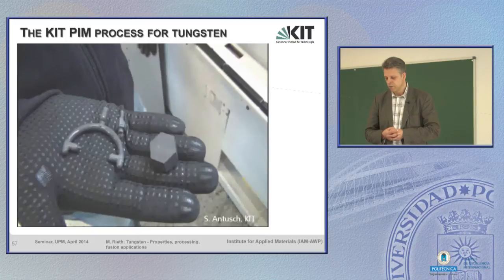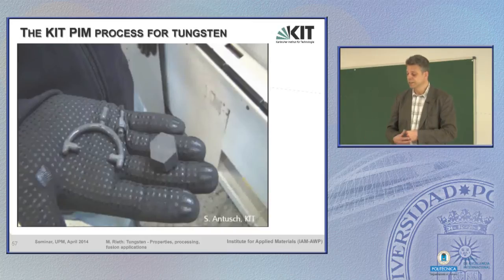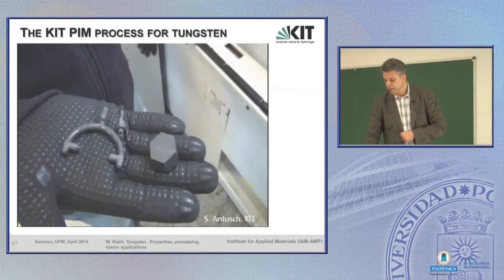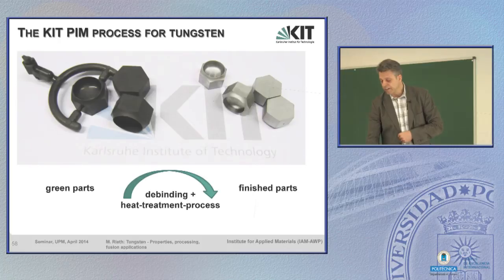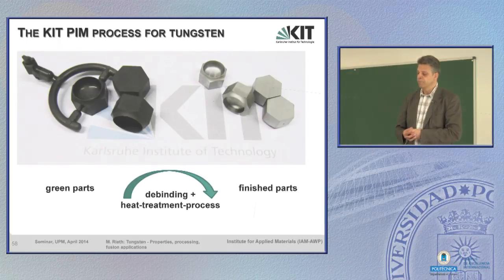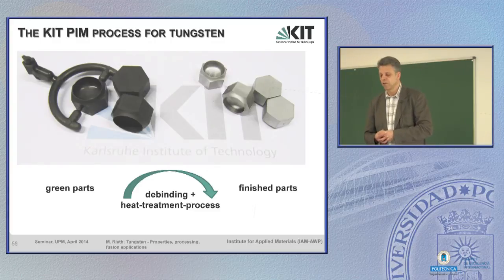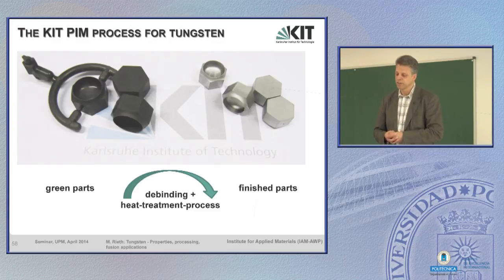That's the pressed tungsten part. And after this, the part is sintered, as said. Then it shrinks, always during sintering, and you end up with nearly, or rather good, near net shape parts.